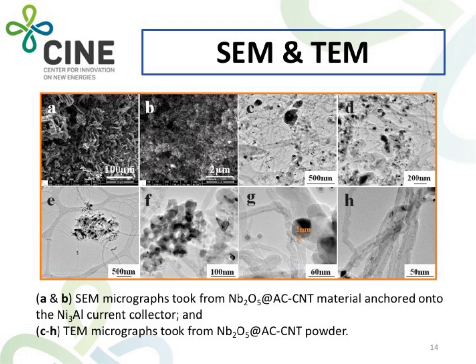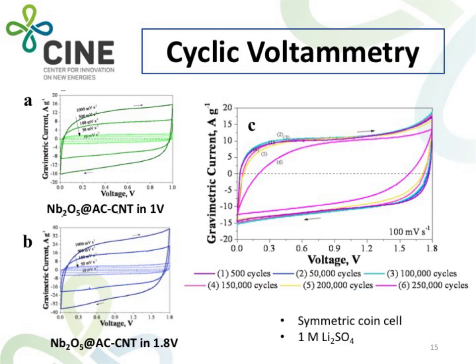Okay, let's look to the electrochemical studies. First, we have in figures A and B voltammetric curves using different voltages. In figure A, using 1 volt, and in figure B, using 1.8 volts. And the main point of this slide is figure C, on the right side of this slide, where we have the voltammetric curves as a function of charge and discharge cycles. Here, in this case, it goes from 500 cycles to 250,000 cycles. And even after a lot of cycles, the cyclic voltammetry has a very good shape.